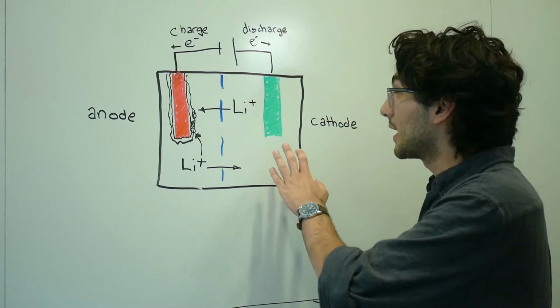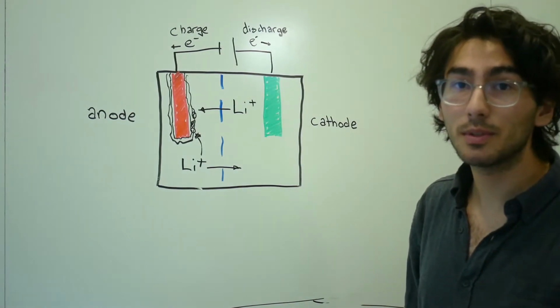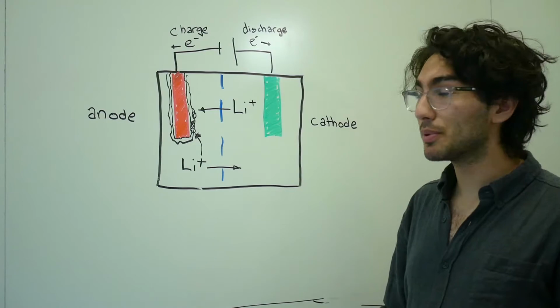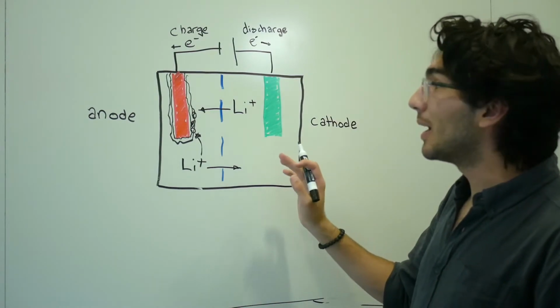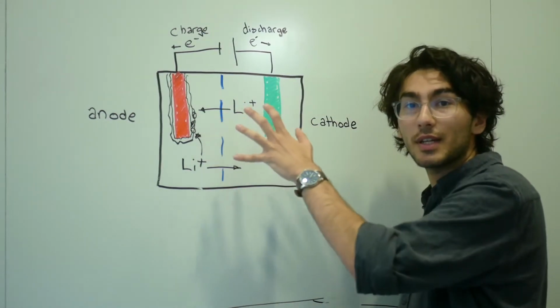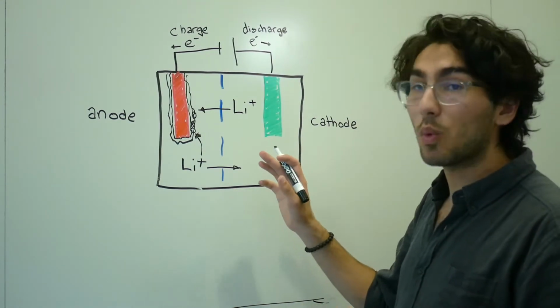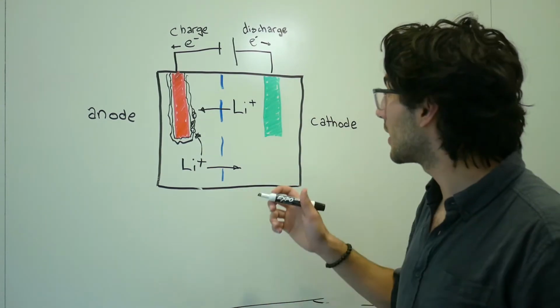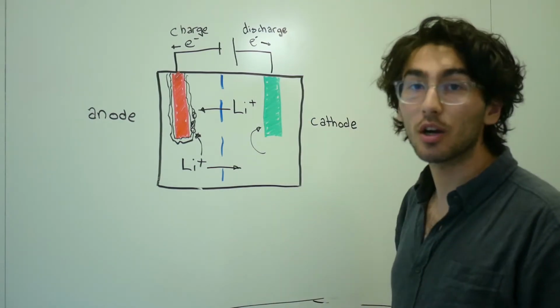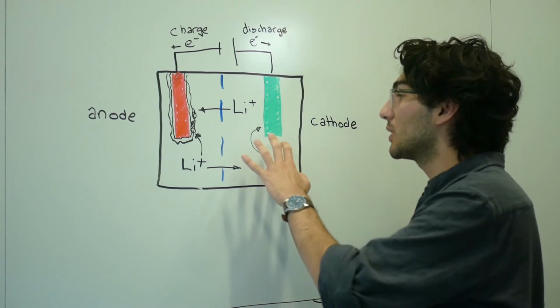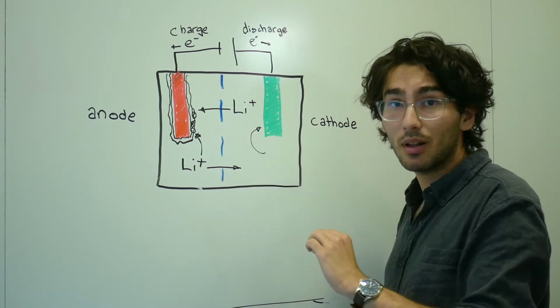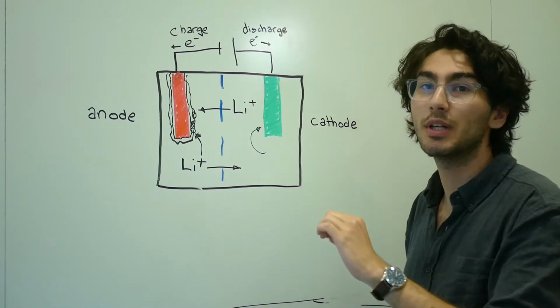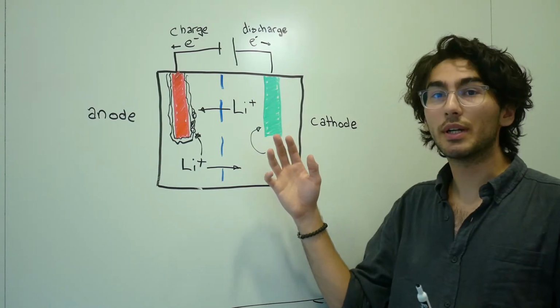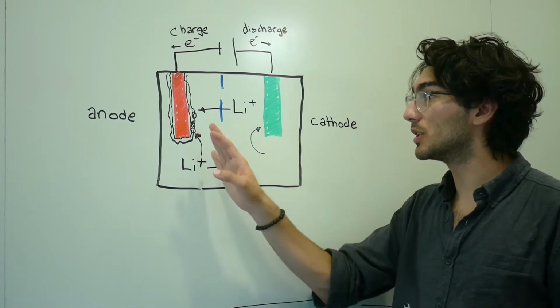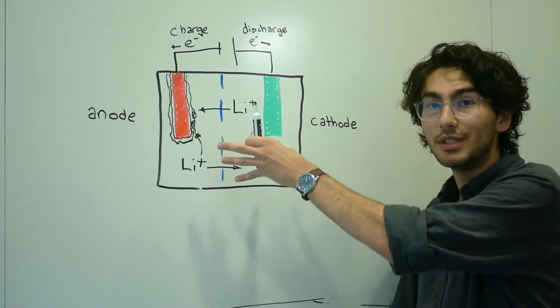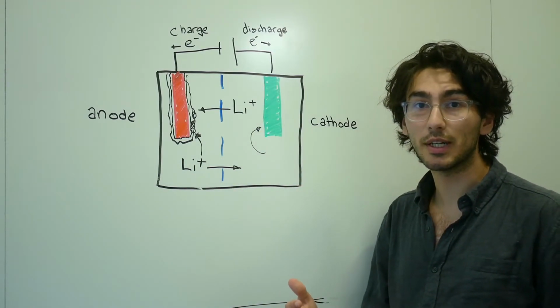Now, the second thing that can happen with positive electrode decomposition is if any moisture makes its way into the battery. Because of the makeup of a lot of the chemicals used in the battery, mixing with water can actually create acids in the battery. And what these acids do is they attack your cathode. And what that's going to do is bring transition metal ions from the cathode into solution. And just like with disordering, now that you have transition metal ions in solution instead of lithium ions, you're going to decrease your battery's performance over time.